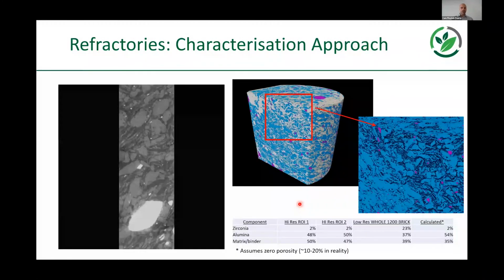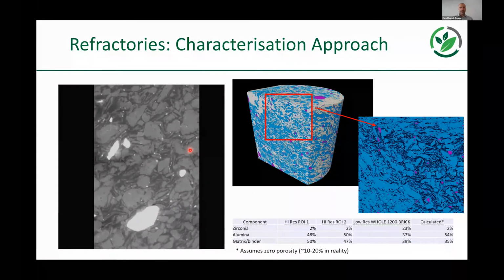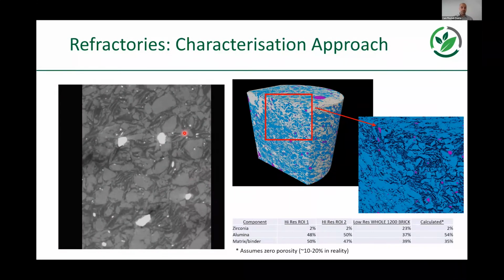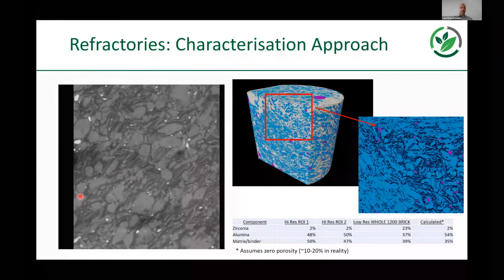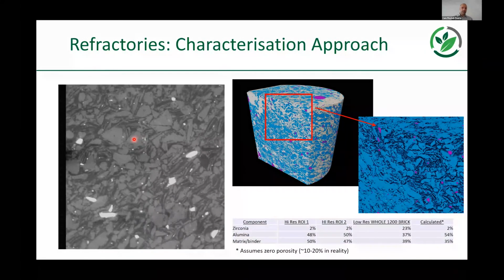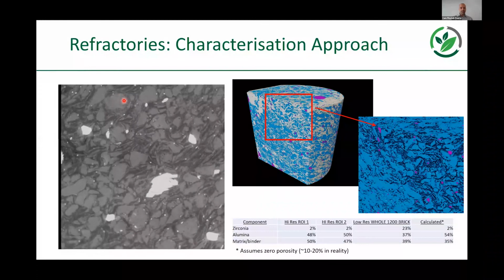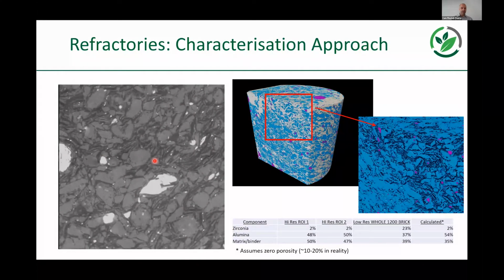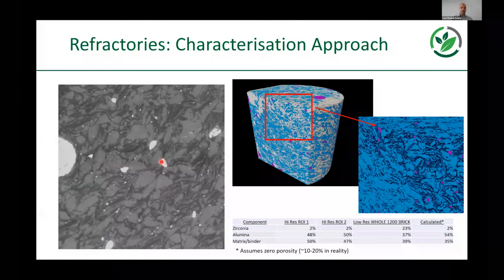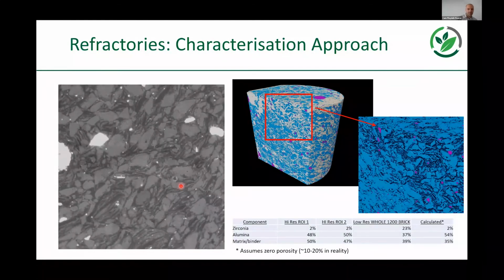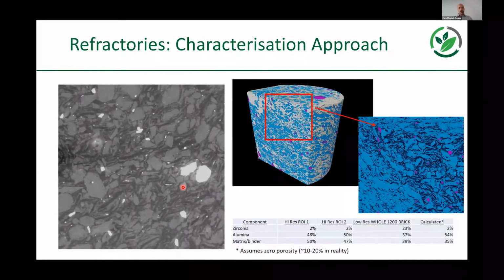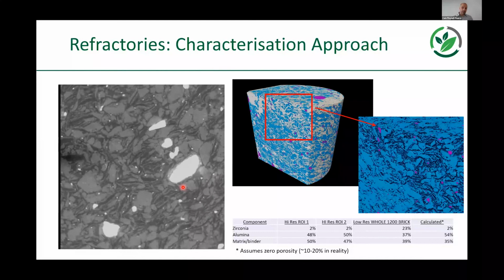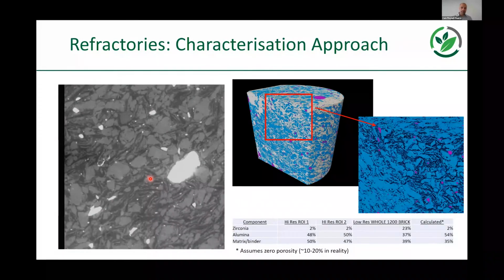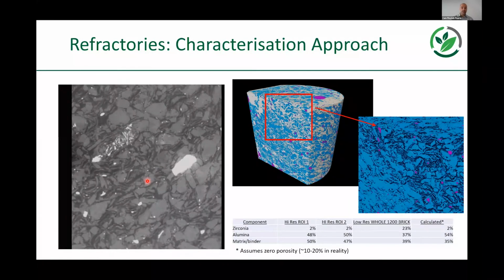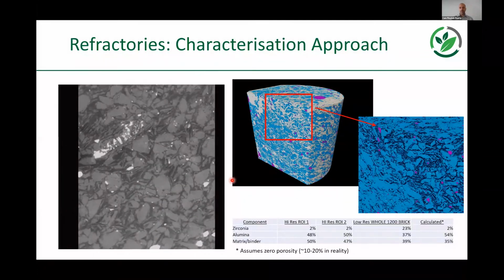So we wanted to look at what does that look like in the context of refractories. On the left-hand side of the screen here, you can see a fly through, a series of slices going through a refractory. These are the rocks. In this case, it's alumina graphite or alumina carbon system, and the bright spots here are some zirconia material, which is used for toughening and improvement of resistance to thermal shock, and I'll explain why that's important in a minute.